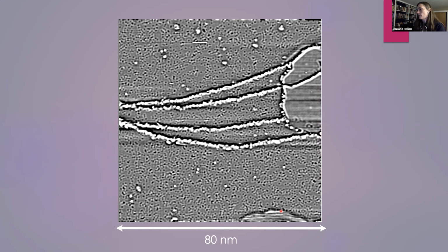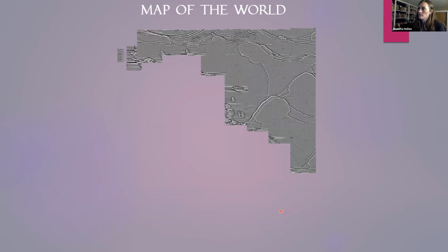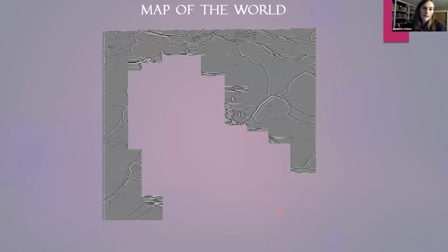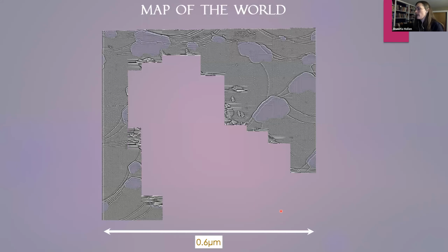But then if we wanted to go around and find out what the world looked like to the STM, if we wanted to access all of the regions of space that the STM could access and look at the whole sample surface from the perspective of the STM, we would have to take a lot of images. So this is the entire region that the STM can reach after you get your experiment all set up. So this is the world according to the STM. And this copper surface we were studying because we were trying to grow graphene on copper. And these smooth little islands here that I just colored in purple, those are all graphene islands that we grew on this copper crystal. And this whole thing is a little bit bigger than half a micron.